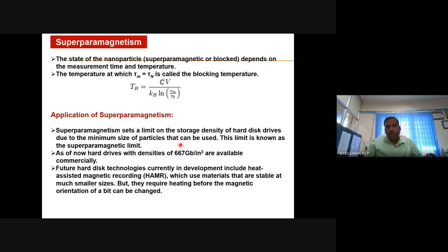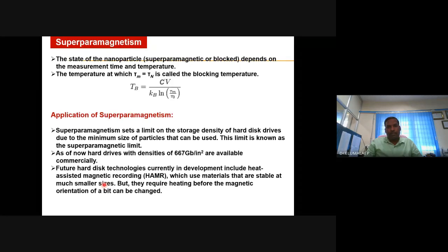And this will become the basis for data storage. Currently, this much is the data storage capacity, 667 gigabytes per square inch. But with this Néel flipping time or Néel relaxation time associated with superparamagnetic materials, in the name of heat assisted magnetic recording, HAMR, there is going to be unlimited data storage in a given smaller grain material. The only requirement is you will have to place that, maybe an SD card or anything, at a slightly elevated temperature, depending on the material. Then it will become an unlimited data storage device using HAMR. That is why these nanomaterials have become fascinating.